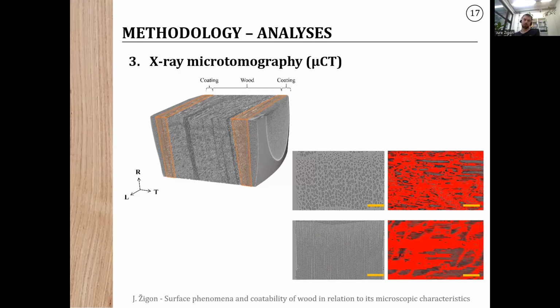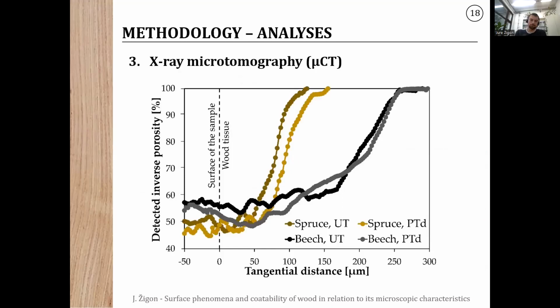But anyway, we were reslicing these 3D models of the scanned samples, and then using simply ImageJ, we were detecting or measuring the porosity versus the tangential distance from the surface inside into the sample. So here is the result, for example, how the presence of the porous structure is increasing with the tangential distance into different wood species. So this is one example of how we did it. We could do it also another way, but in this case, we were using this approach.